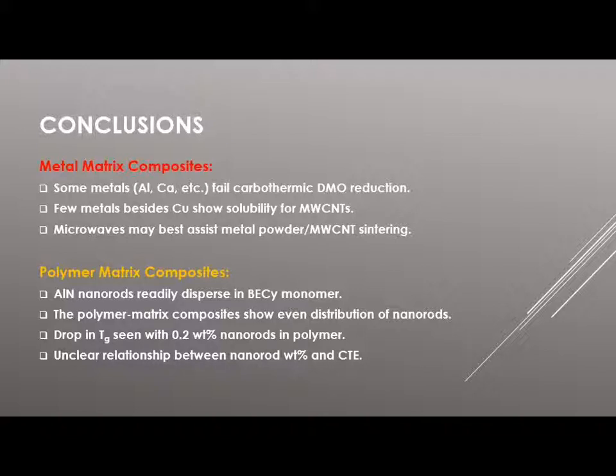So it looks like the better option here in making these composites, if you're wanting to use the microwave route, is to take pure reduced metal in particle form and add the nanotubes directly to that and mix it all together, and just work on sintering the metal and the nanotubes with the microwave heating. Because the actual reduction of the metal doesn't work in certain cases where the reduction potential can't be overcome, and other metals just aren't showing good solubility for the nanotubes.